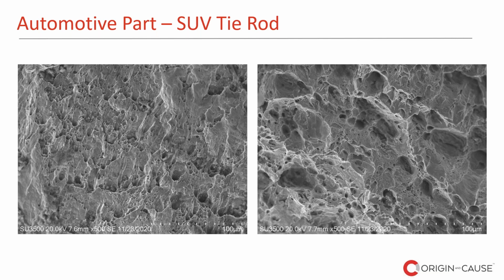In this particular case, these images are taken at 500 times magnification. Those features that you see here are so-called dimples, and they are always associated with a ductile failure. In other words, the tie rod was overloaded. Although it might sound weird, in material science, oftentimes we say the material failed as intended. The materials are designed to withstand a certain stress, but after that stress is exceeded, the material will fail, and it will fail in a ductile manner. So in this particular instance, because the tie rod failed as a result of ductile overload, it was concluded that it failed after the accident and it was not the cause of the accident.